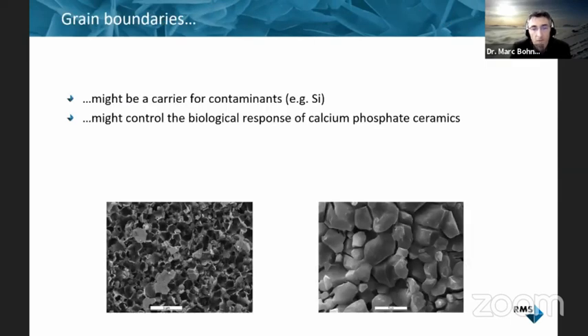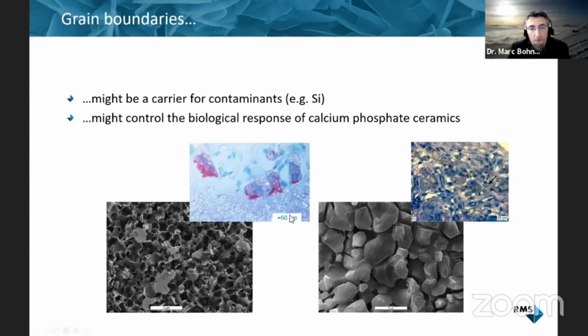And so we've been observing funny things over the years in my lab. For example, here, two beta-tricalcium phosphate ceramics that are dissolved in aqueous solution. In one case on the left, you see that the grains were more unstable than the grain boundary. So you have a grain dissolution. And on the right-hand side, this is the typical behavior where the grain boundary is dissolved and the grains remain where they are. And so actually we could postulate that maybe on the left-hand side, we would mostly have an osteoclastic resorption because the cells need to go to the surface in order to degrade the material. And on the right-hand side, we might have the release of particles, and then the resorption would be maybe induced by macrophages.